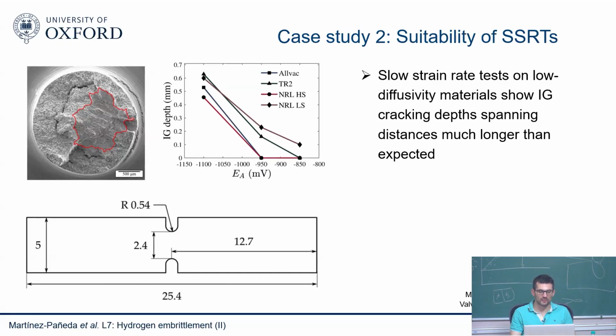However, the colleagues that we have at the UVA, they have been a bit critical of slow rate tests, and they were a bit puzzled by a number of things. So one thing is that, these are all experiments on nickel superalloys. So nickel has a very low diffusivity, as FCC, very low diffusivity. And these are not experiments where you pre-charge all of your sample. You pre-charge maybe sometimes 24 hours or a couple of hours, and then you start loading. So basically, most of your sample is not exposed to hydrogen. Only the surface is exposed to hydrogen, and then hydrogen diffuses into the sample. And what they see is that this is the intergranular depth.